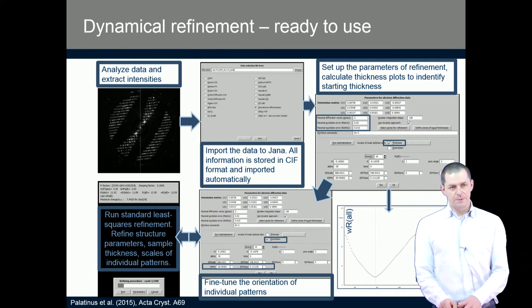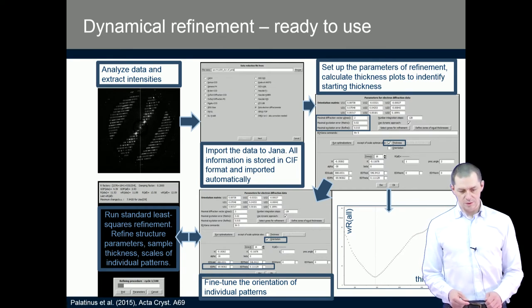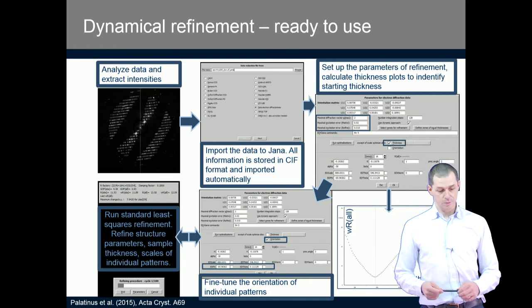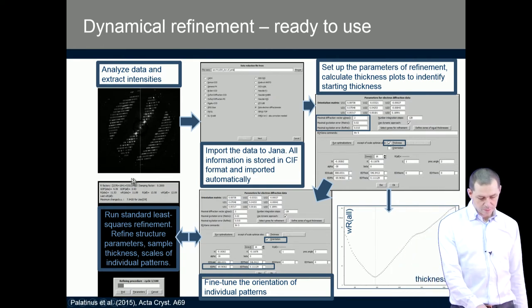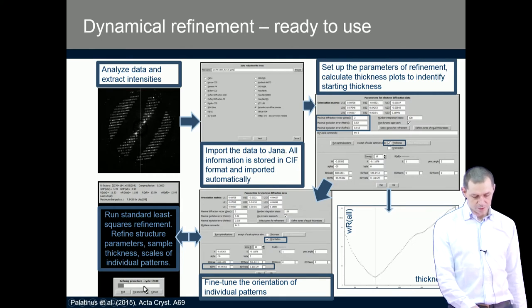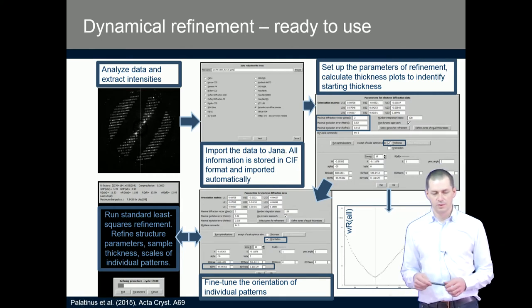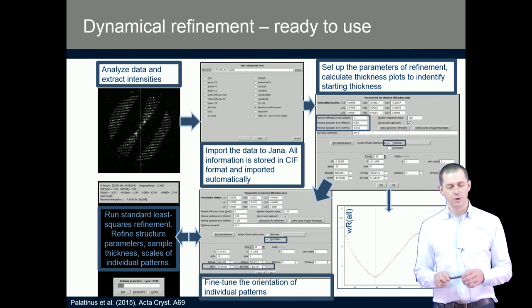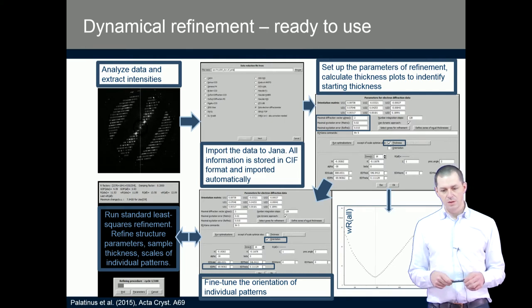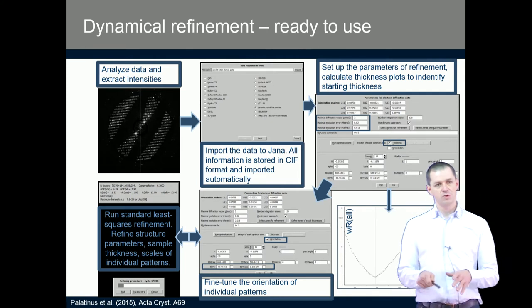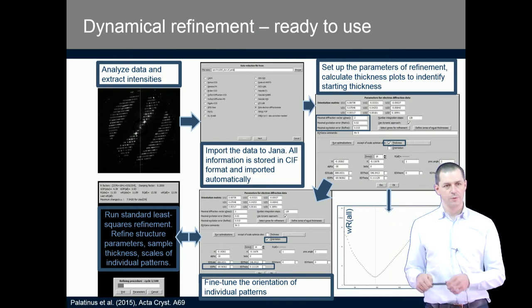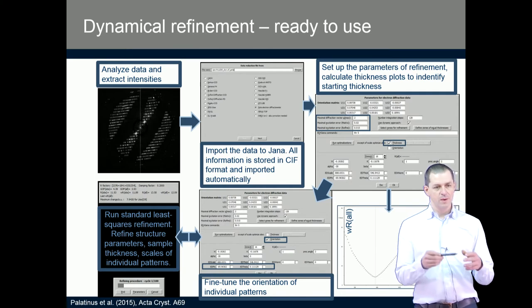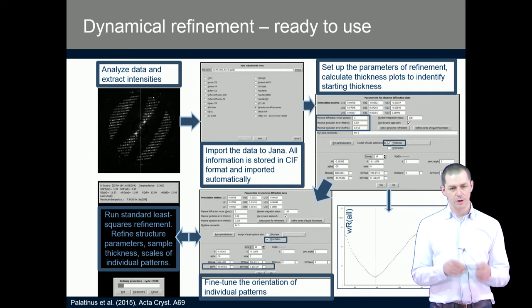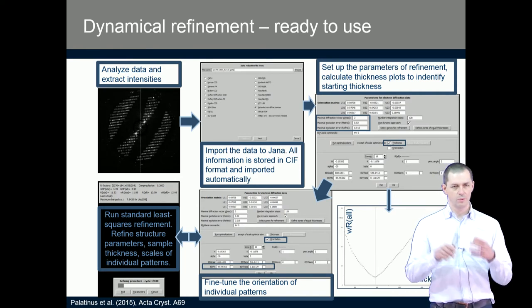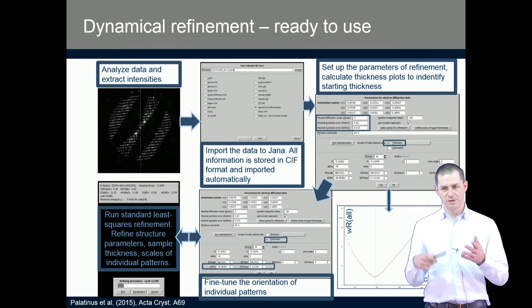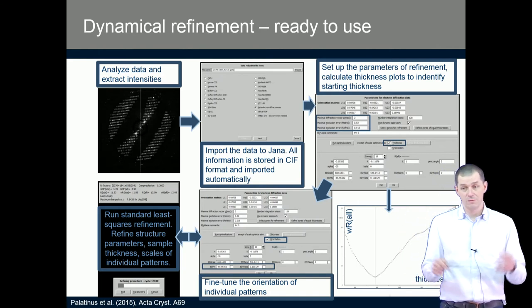And then after you set up these parameters, you will do it this afternoon in the practical work, you will see that it is not so complicated. Then you run just a normal refinement. You see the normal table of R values and the progress of the refinement, and you refine the structure in a way completely analogical to the refinement of X-ray data. So apart from a few things you need to know that are special to the setup of dynamical refinement, most of the refinement is the same for electron diffraction data as for X-ray data, including calculation of difference Fourier, modifying atomic types, defining disorder if there is some, and so on and so on.